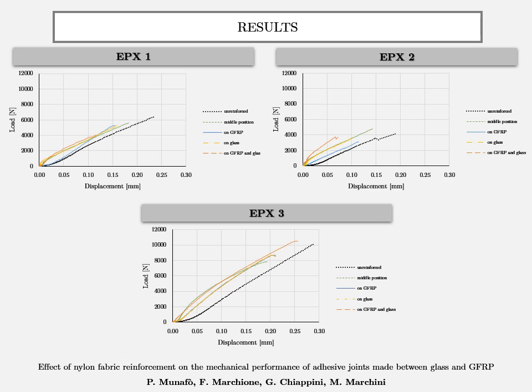Load displacement curves for reinforced and unreinforced configurations for double-lap adhesive joints are shown here. The use of nylon fabric causes a decrease in the ultimate strength for almost all applications. A reduction in the ultimate displacement is observed, accompanied by an increase in the stiffness. The third epoxy adhesive offers the best mechanical performance in all configurations with nylon reinforcement.